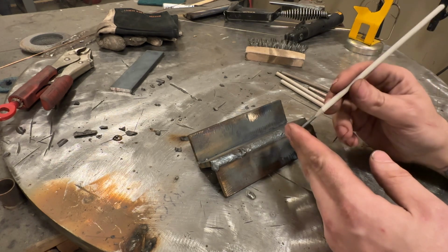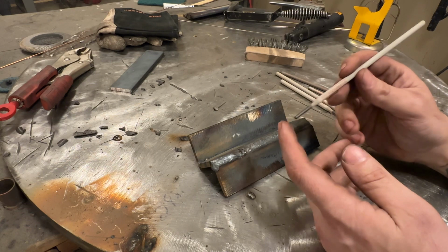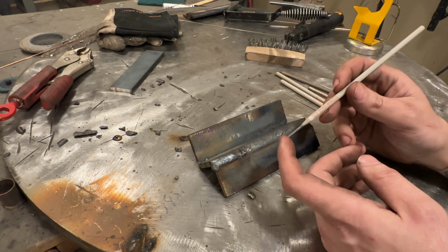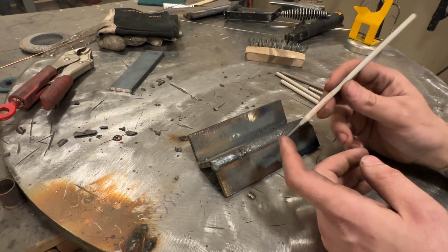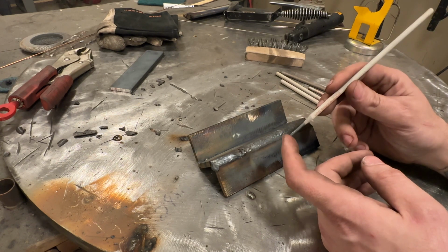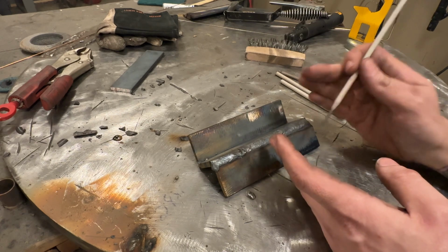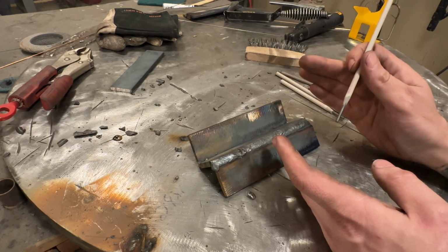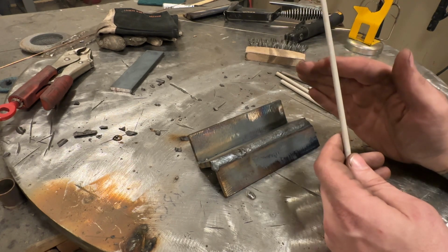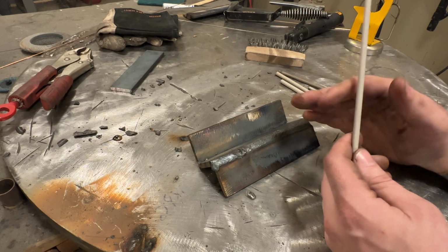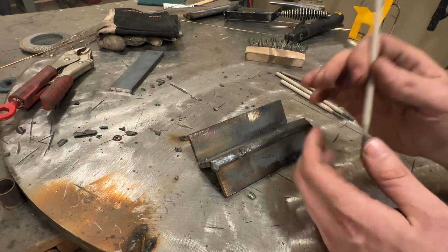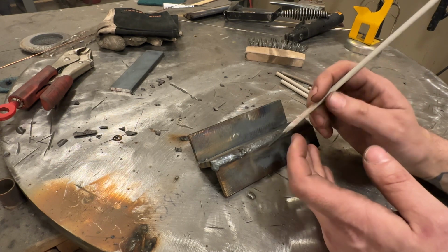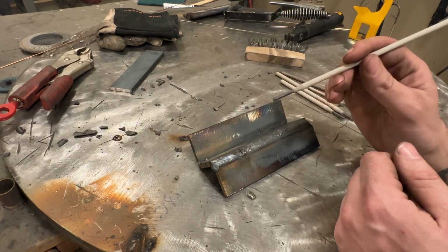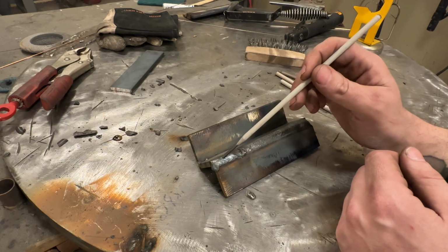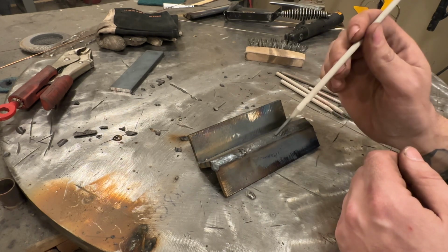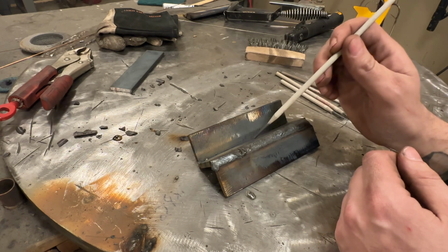So these rods are spec'd out as a 7018 at 70,000 PSI tensile strength. Normally, these actually test in destructive testing closer to 80,000. So they actually test higher than spec. Spec says minimum. If it tests over, it's okay. There are some codes that say, hey, if this thing tests at 90,000, that's too much. So there are codes that can say nothing over, nothing under. But for this, we'll say 70,000 PSI tensile strength, commonly tests at 80. Depending on how you lay down this weld, can change the tensile strength to drop it below specification.